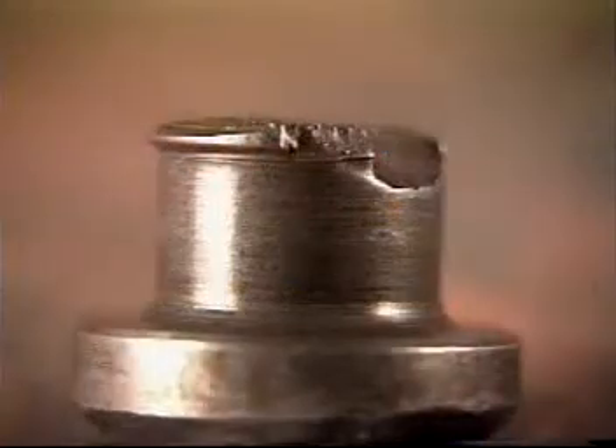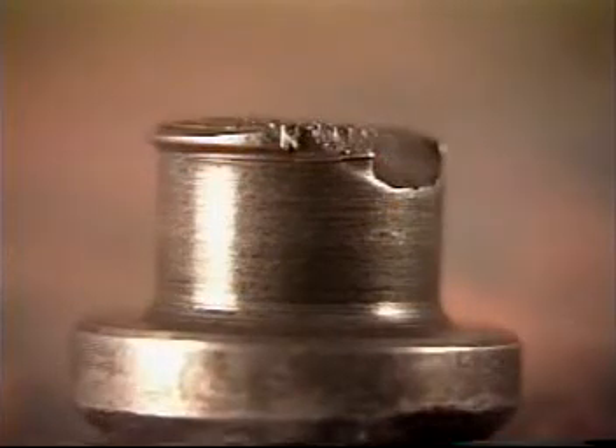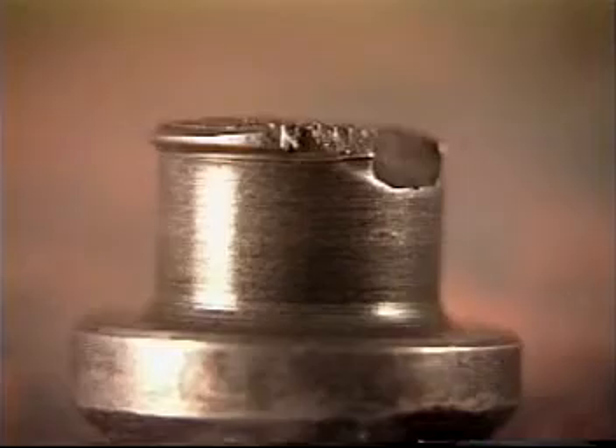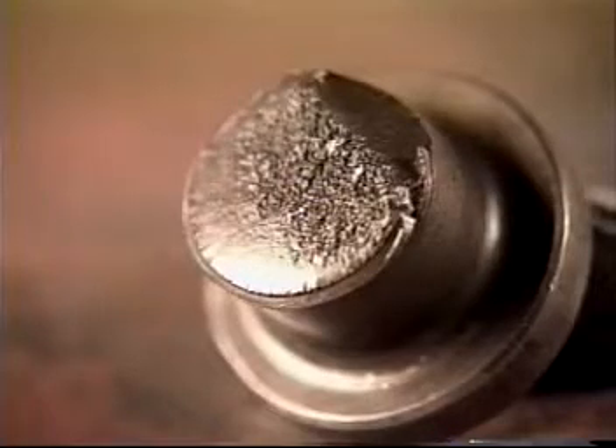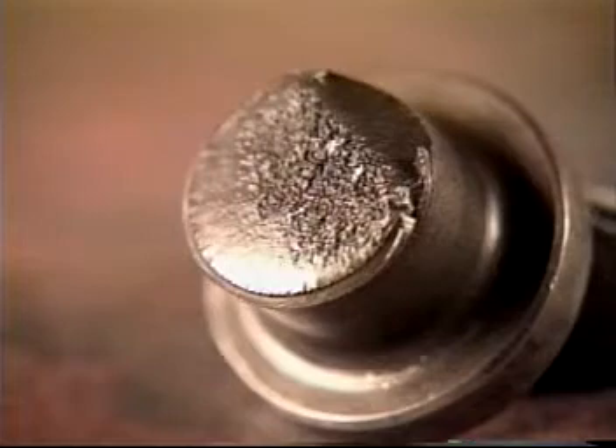Typical loss of displacement failures on sucker rods will result in the pin breaking in the first full thread root above the stress relief. Pins will normally show a small fatigue area and a rather large tensile tear area. Other break configurations will vary depending on the loading conditions of the rod string.